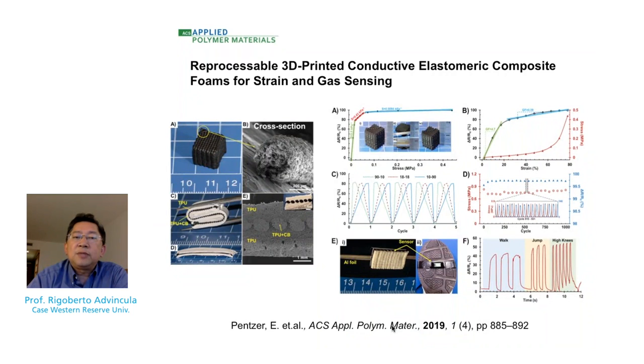So the active ingredient was part of the formulation, namely graphene, and we also added carbon black. And as you can see here in this very busy slide, we are able to control or detect the change in conductivity or resistivity as a function of compression or release of compression or actuation. So in other words, this material, as reported, has been used as a motion sensor where we can distinguish between running, walking, and standing or jumping. And at the same time, this material also is a good gas sensor. So in this case, 3D printing allowed us to make the object and composition at the same time, but we embedded the electrical or resistance function on the material.